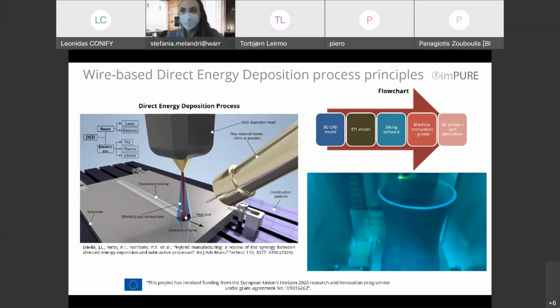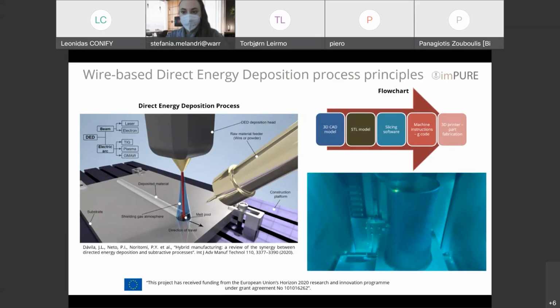We have an in-house wire-based direct energy deposition system. What we do essentially is we use a laser beam to melt wire material that is fitted coaxially from the head to the substrate. The laser creates the melt pool, and we deposit weld track every time, layer by layer, until we can complete our 3D printed part.